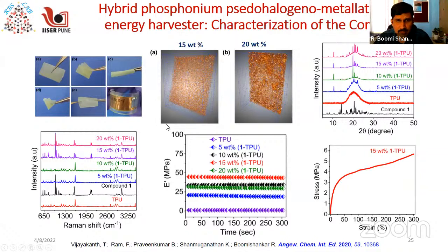3D X-ray tomography is similar to scanning electron microscopy, except that the probe in this case is not an electron beam, but an X-ray. So this becomes a softer technique compared to SEM, so that the polymer will not degrade during the measurement. That gives a precise measurement of the nature of the particles embedded in the polymer matrix. I have blanked the polymer background so that only the ferroelectric particles are visible. As you increase from 15 weight% to 20 weight% of the material, agglomeration happens, which is not good for the performance of the material.